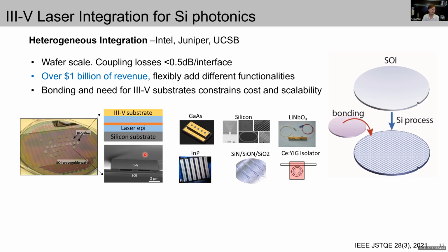So the heterogeneous integration: on one hand, you can bond different materials to the SOI substrate, for example gallium arsenide, III-V materials like lithium niobate. And you can also bond this SOI to different substrates, for example silicon carbide, which is also a very interesting substrate because of its thermal properties, and probably some 2D materials. These are all possible. That's the beauty of heterogeneous integration. It's very flexible. It can accommodate different materials despite their different material qualities.